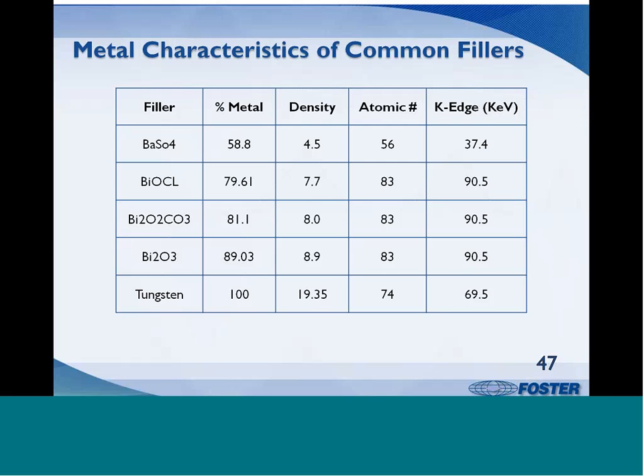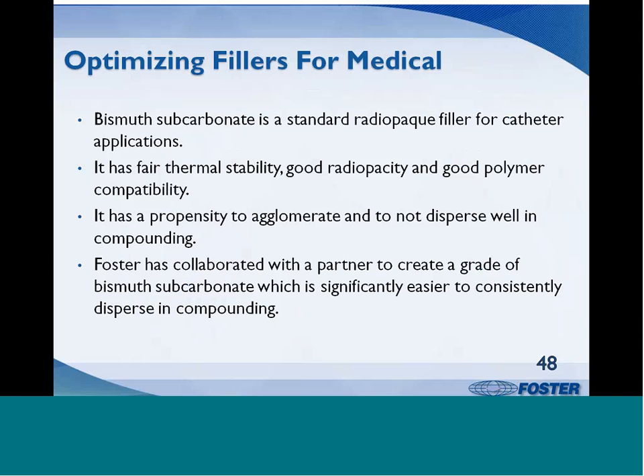Bismuth trioxide has the potential to be the best all-around radiopaque filler, but it trades radiopacity with processing, color, and stability issues. Bismuth subcarbonate has good radiopacity, color, and thermal stability, but suffered from agglomeration issues. To improve dispersibility, Foster worked with a partner to create a new morphology which has been shown to disperse consistently better than the old standard grades. This new material is being used in an ever-increasing number of new catheters.